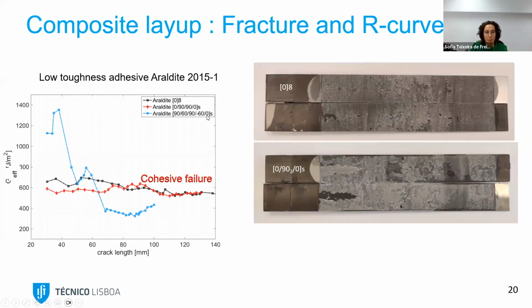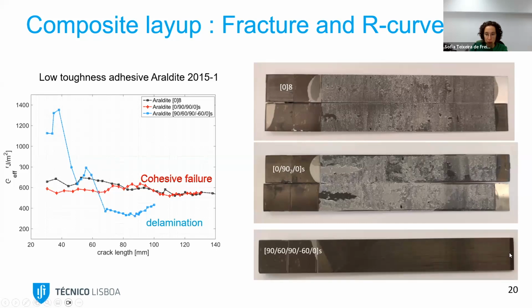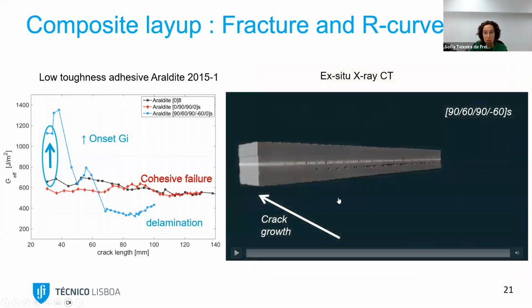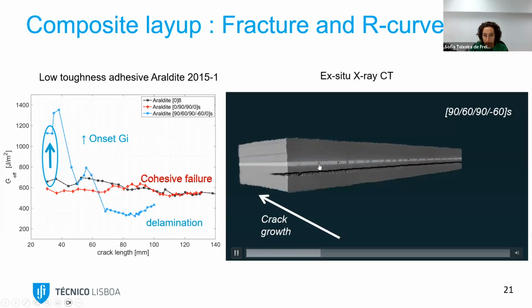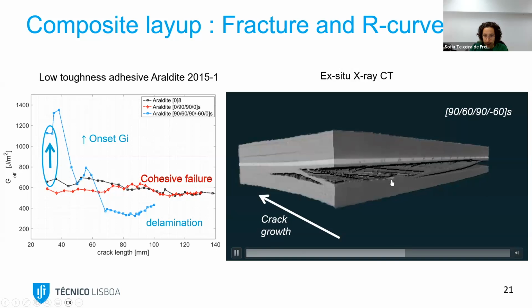However, when we look at the non-conventional laminate, with 90 and 60, what we see here in the energy is that we have a significant increase in the energy in the beginning, and then we see again a low energy at the end. So looking at the fracture surface, what we see is 100% composite failure. We don't see any adhesive. And so we try to understand why we had this increase in the beginning. What we did was a CT scan, which is computed tomography, where we use X-rays in order to visualize better what is inside the specimen. And this is what we saw. So here you see the adhesive is the lighter area, and here is the crack that is propagating inside the composite.